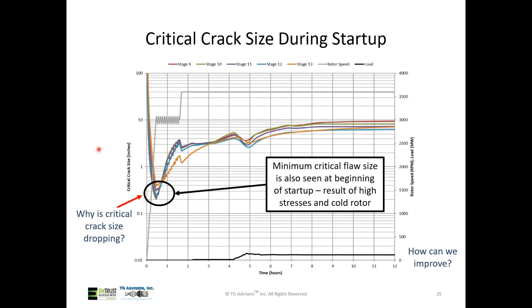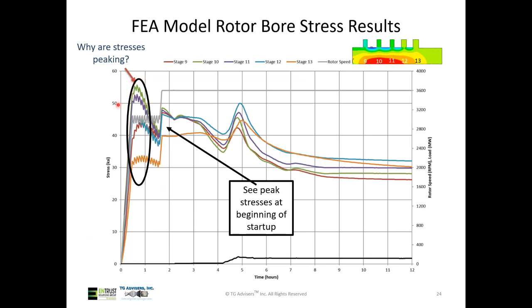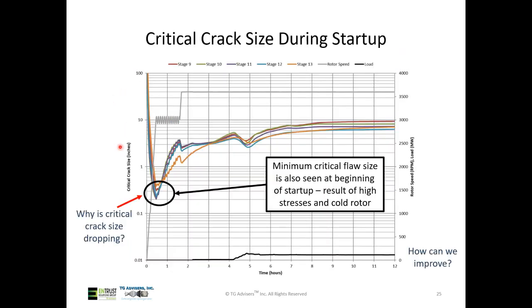So what we're seeing, because we get those high stresses at that point and we have still poor material properties, so brittle behavior, we get a very big dip in the critical crack size. So that's my point of the startup that I'm most susceptible to failure. And this is saying like 0.2 inch crack depth.